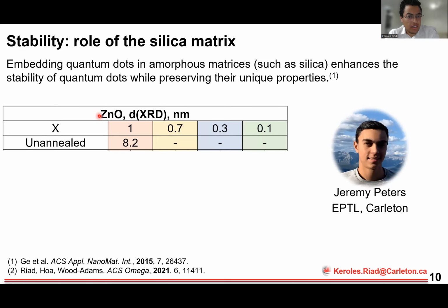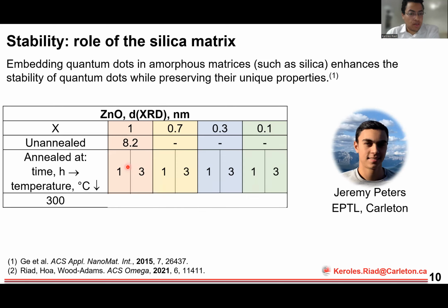Essentially, he made zinc oxide particles, and here it's preliminary data, it's incomplete, so there's a lot of work left to do. But essentially, with XRD, we're only able to measure crystal size for the pure zinc oxide, because once the crystal size is very small, and with the amorphous silica, it actually becomes impossible to measure crystal size with XRD. But as you anneal those particles at 300 degrees C for 1 hour or 3 hours, for the pure zinc oxide, the size increases from 8.2 to 13 nanometers, which is a 60% increase in size.